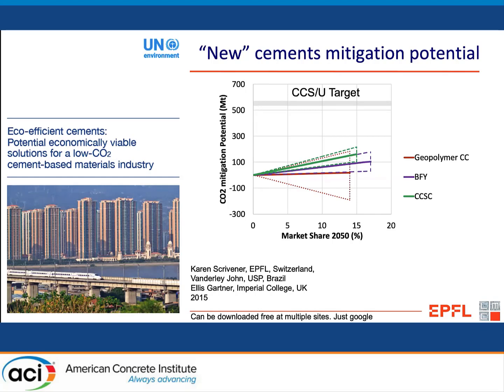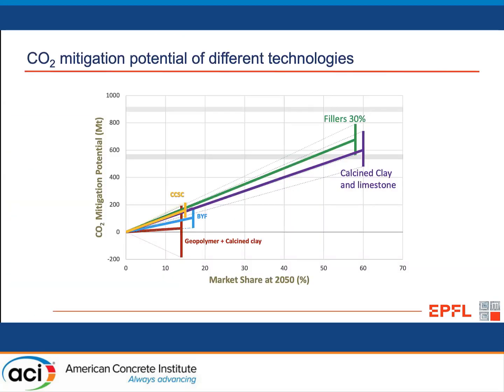We looked at alkali-activated materials based on calcined clay, which do have this almost unlimited availability. And you see this huge margin in whether you actually save any CO2 at all. But irrespective of whether you save CO2, I think what's much more interesting is to compare these new materials with two ideas that we have tried and proven, and we know have absolutely massive potential to reduce CO2.